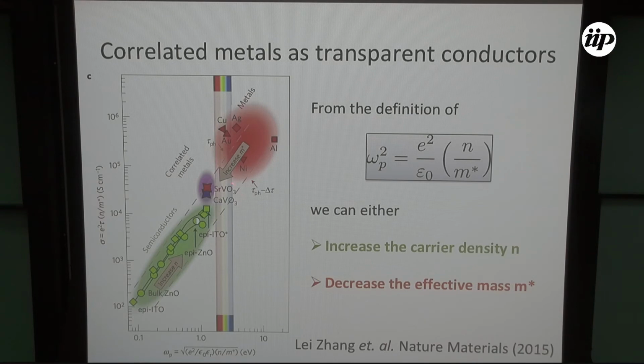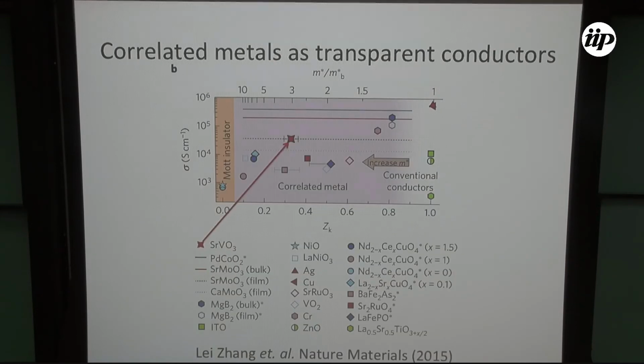So the two candidates, the most prominent candidates, are strontium vanadate and calcium vanadate. They have plasmon frequencies as small as 1.33 electron volts. They are to the left of the edge of the visible, and they have conductivity much higher than the best semiconductor made. So these are two nice candidates to make photovoltaic devices.